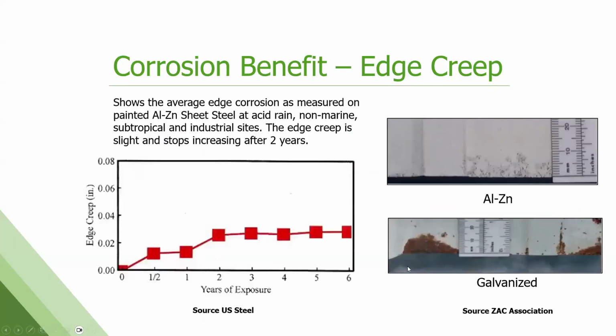And here's an example, right? Pictures are great. The pictures on the right here are an aluminum zinc painted product and a galvanized painted product, painted with the exact same paint, put out at the same time of exposure. And you can see that this is after like 5 or 6 years or 2 years. You can see that there's red rust. We call this edge creep on the galvanized. The top picture, the aluminum zinc product, yeah, there's some corrosion going on there. You can see that the edge has gotten a little rough and discolored, but you're not down to red rust and you're not losing paint off of it.